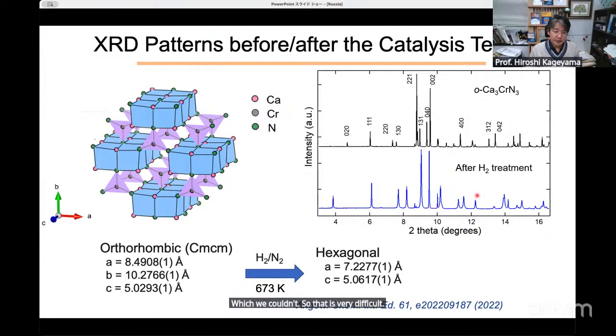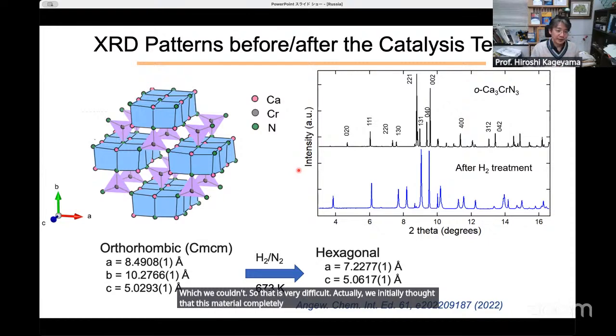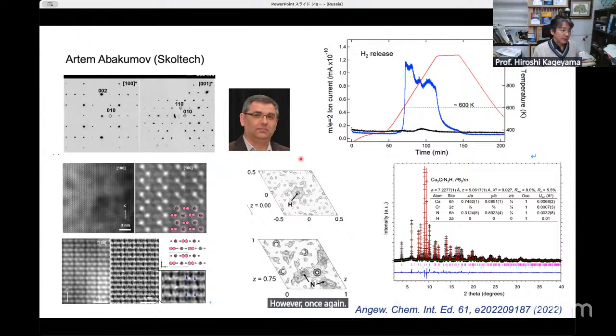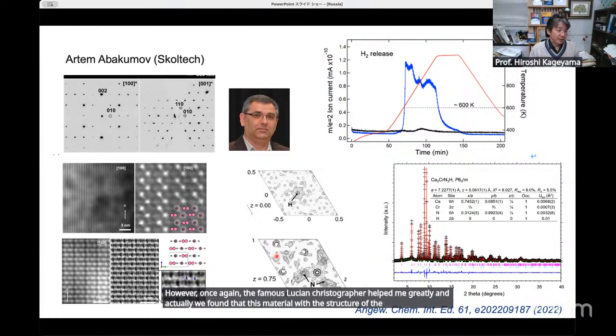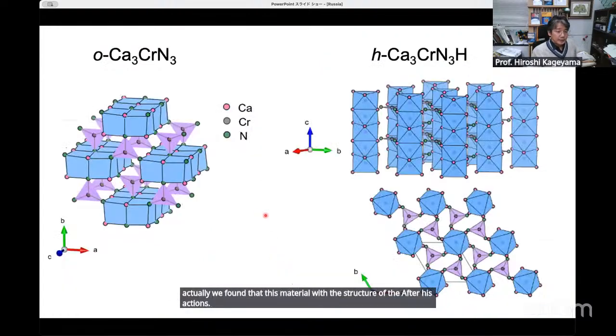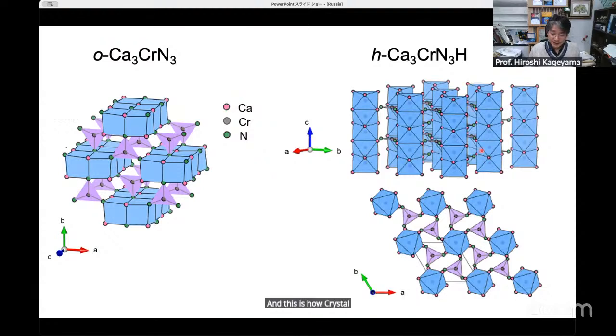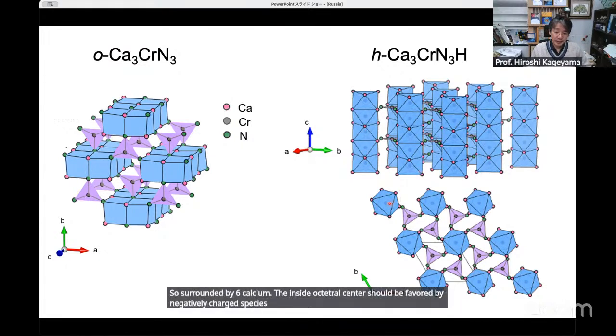Actually, we initially thought that this material completely changed into a completely different crystal structure. However, once again, the famous Russian crystallographer helped me greatly, and we found the crystal structure of the material after ammonia catalyst reactions. This is how the crystal structure looks. This is hexagonal. You can see that these octahedral chains are running parallel to the c-axis. Additionally, we found that the hydride is not a proton, it's H minus, positioned at this octahedral void surrounded by 6 calcium atoms. Calcium is highly electropositive, so surrounded by 6 calcium, the octahedral center should be favored by negatively charged species. That's why the hydride is located here.